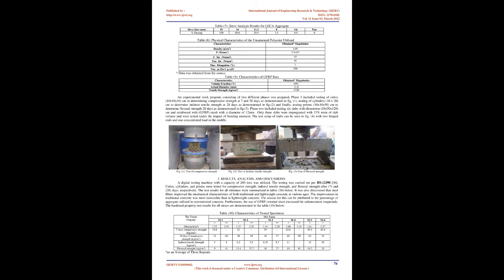and storage water tanks. Victor Yehia et al., 2003: Polymer concrete, PC, composites have a different set of characteristics that vary depending on the formulation. The variations in polyester polymer concrete mixture components that affected the characteristics were examined in this study. The impact of resin content, aggregates, fibers, and coupling agents was scrutinized. It was discovered that the optimum polymer content ranged from 12% to 14%, W/W. Utilizing fibers and coupling agents improved the mechanical characteristics of PC even more. In addition, a new database was created to document various PC characteristics.